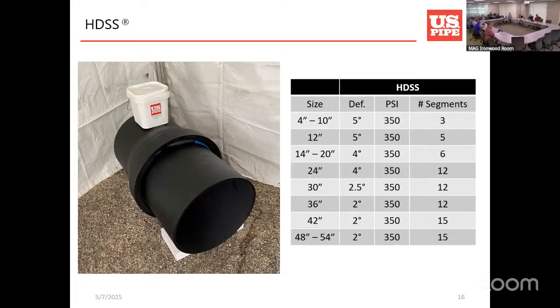And then by only inserting the locking segments through the 12 o'clock position too, there's safety in mind there. So the contractor's not reaching down underneath the pipe to like the 7 and 5 o'clock position. They're only inserting those locking segments through the 12 o'clock position. And what's good about it too is you can see all the deflection capabilities, and you can see why we have that. 30 inches is a really good example. 2.5 degrees deflection while rated at 350 PSI, as compared to that HP lock, which was only a half a degree of deflection while rated at 350, as compared to the TR Flex, which is 1 3/4 degrees deflection, but only rated at 250 PSI.